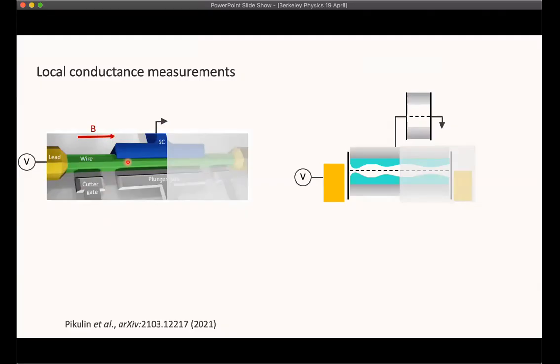But importantly, for the topological phase, what we expect is that it extends the entire length of the wire, as in the Kitaev model, where the entire chain was in a topological superconducting phase that allowed for unpaired Majoranas at distant ends. And those unpaired Majoranas are now in some very long distance, non-local entangled state, which is important for our quantum computation. And so, of course, these measurements are now prone to any of the disorder that is present on this local single side of the device. But perhaps you can see through my shaded box here and see where we're going with this.